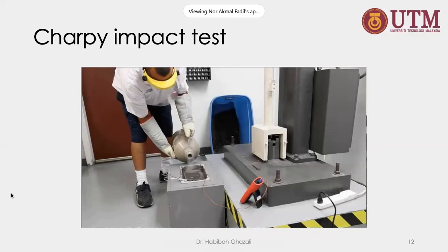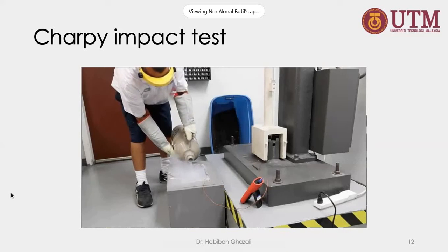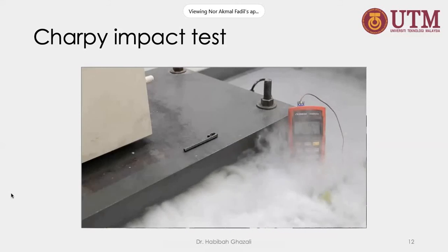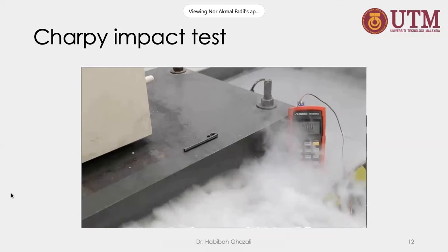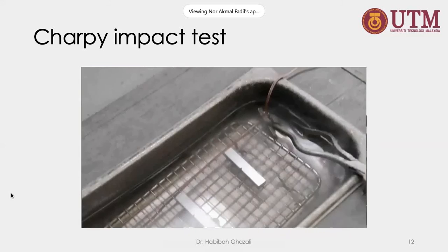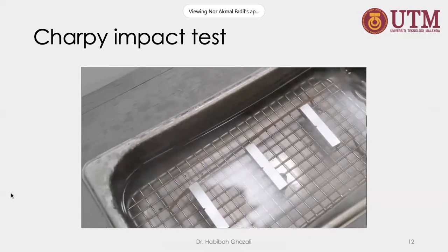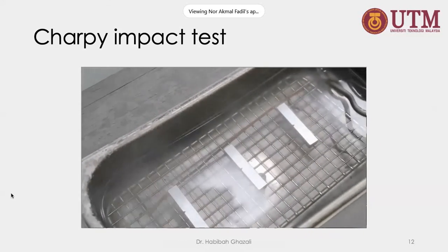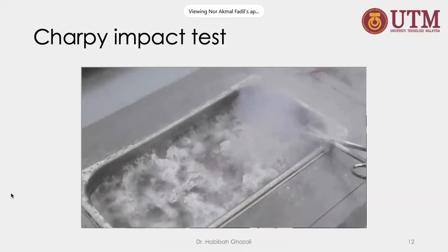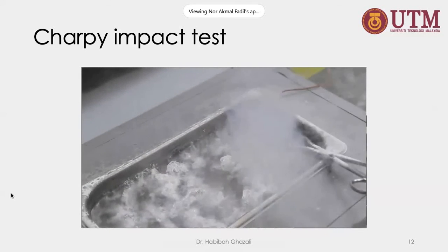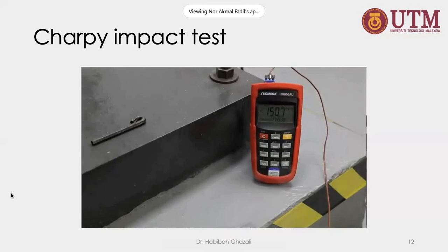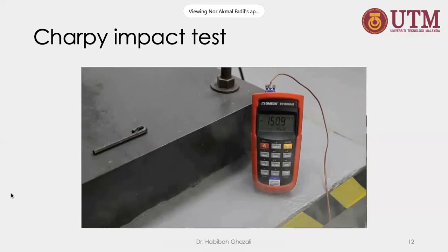Depending on the type of material, the specimen can be tested at between an ambient atmosphere to minus 150 degrees Fahrenheit. The sample piece is an ASTM A320 L7 stud, which requires testing to be conducted at minus 150 degrees Fahrenheit. Once the required temperature is obtained, the specimen is held for a minimum period of 5 minutes.